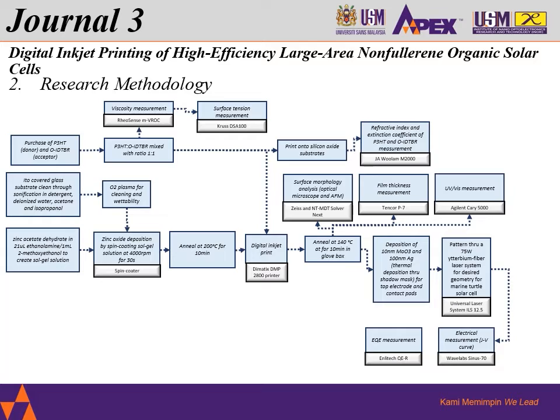First of all, we'll go on to preparing the substrate itself. In this journal, it is using an ITO covered glass substrate, which is cleaned and then goes through O2 plasma for cleaning and wettability. In parallel, we have zinc acetate dihydrate and 21 microliter ethanolamine with 1 milliliter of 2-methoxyethanol to create the sol gel solution.